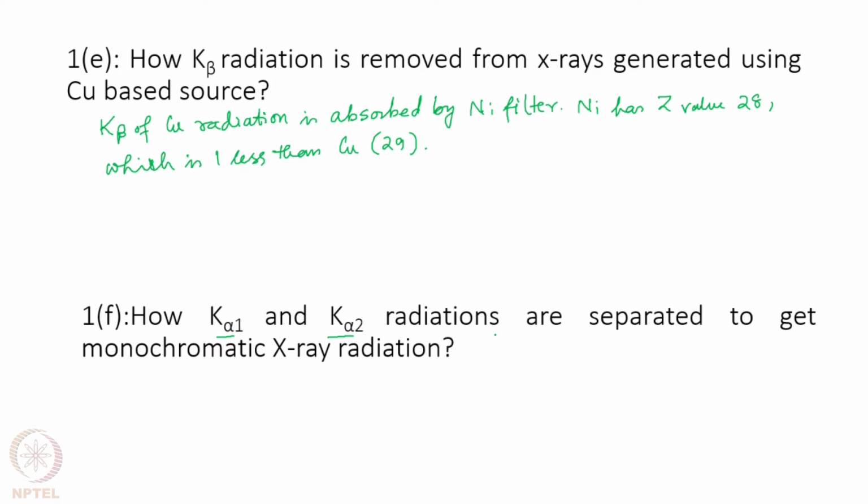This separation is difficult and it also involves a loss of intensity of both alpha 1 and alpha 2, and it is done by using a monochromator, which is actually a crystal of germanium. So, a crystal of germanium is cut along the 111 plane, which you may not understand right now. At the moment take it as the Miller indices of that particular plane, which I will explain later. It is cut along the 111 plane and